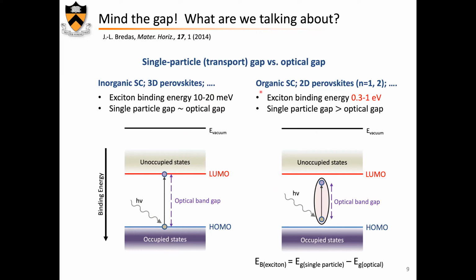Very different in organic semiconductors, where carriers are much more localized, and therefore an exciton formed on a molecule, a microexciton, will have a large binding energy of the order of half an electron volt up to 1 electron volt or so, which makes the optical band gap significantly different and smaller than the transport gap, than the single particle gap. So one has to be careful about that. And in the literature, one often sees optical measurements of an organic material, and people then take this optical gap as the transport gap, and that can be quite wrong.